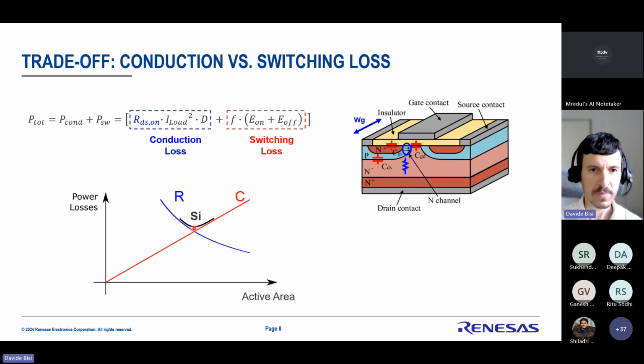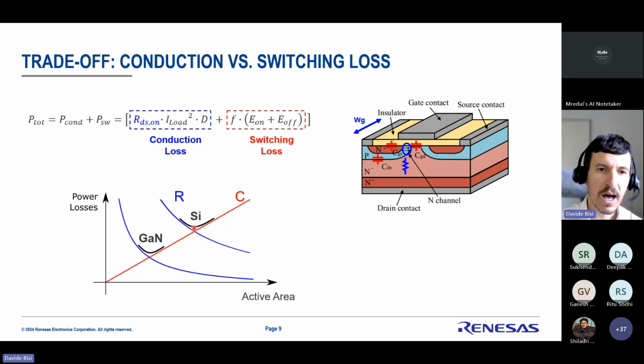Now, what GaN allows us to do is to alleviate this trade-off. For the same active area, we have much less resistance. So GaN for the same area gives you much less resistance. And that means that now the minimum of the power losses is at a much lower position. So we have a lower resistance, lower capacitance, a smaller active area, and smaller total power losses.